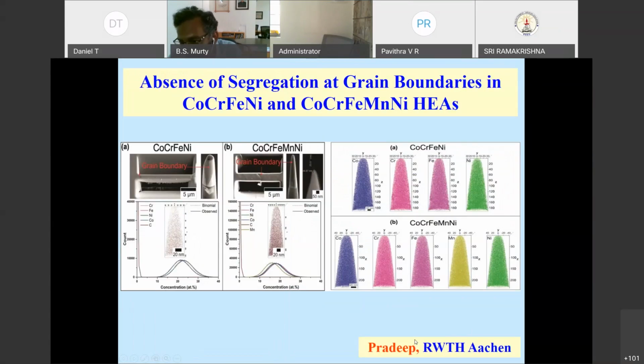We also wanted to see whether there is any segregation of certain elements at the grain boundary in these high entropy alloys. What we can do using a FIB is cut the sample in such a way that the grain boundary is along the axis of the tip of the sample. We can prepare an atom probe sample such that the grain boundary goes from top to bottom along the axis. Once you put it into an atom probe, you can see whether any particular element is segregating at the grain boundary. Interestingly, in this particular alloy, we don't see any such segregation, meaning the elements are uniformly distributed within the grain and at the grain boundary without any special affinity to segregate at the grain boundary.